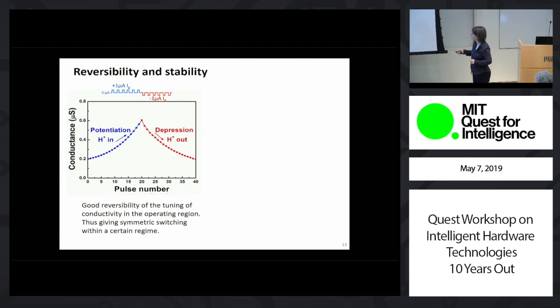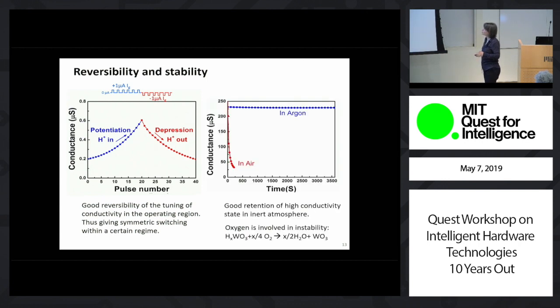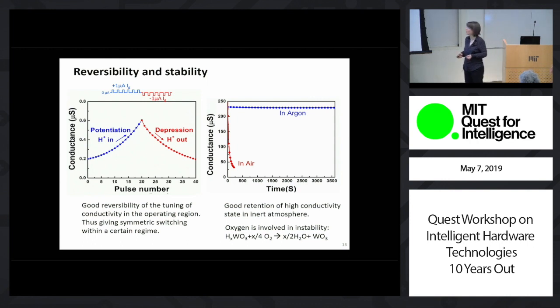in network training. And in terms of stability, if you subject this material to air, proton in tungsten oxide likes to react with oxygen and evolve as water vapor. So if you leave it in air, it's not stable, but if you keep it in inert atmosphere, it's very stable. It keeps its retention very well, which means that if we work with such systems, we must encapsulate them, we must isolate them from air.